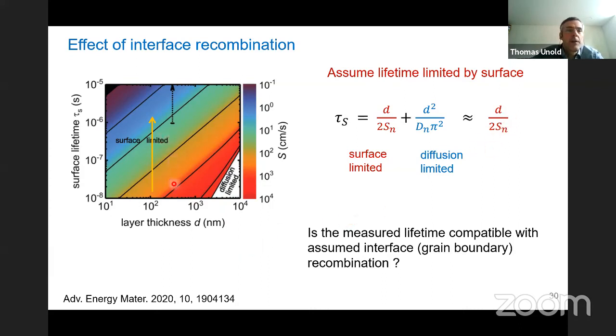So let's say we go now here and take a perovskite device with 400 nanometer thickness. This would be this line here. And we measure a lifetime somewhere, let's say 10 to the minus 6, 1 microsecond. What can you conclude about the surface recombination? So you would look basically here, actually you have to look at the color code, but it's more or less identical.